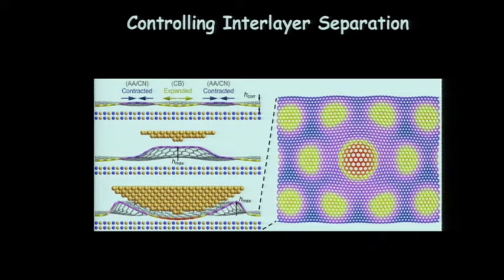And so essentially, when that occurs, the graphene doesn't see the substrate as much. So it loses this matching to the substrate. And then everything becomes back either to the normal graphene lattice constant or something near there. When you press down with the tip, so you get very close to the sample, you're basically changing the gap between the graphene and the substrate. That's going to enhance the interactions between the two, and it's going to favor this carbon over boron. So it's going to want to make a commensurate matching under the tip. And so the graphene lattice will strain when you're pressing down on there.